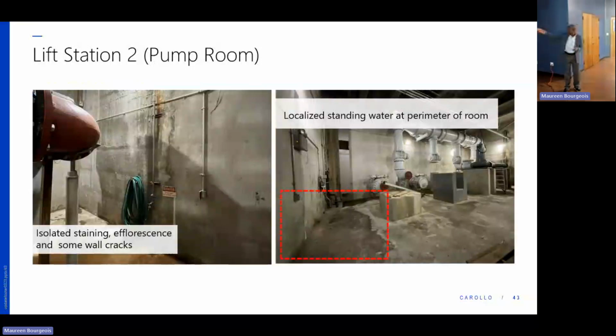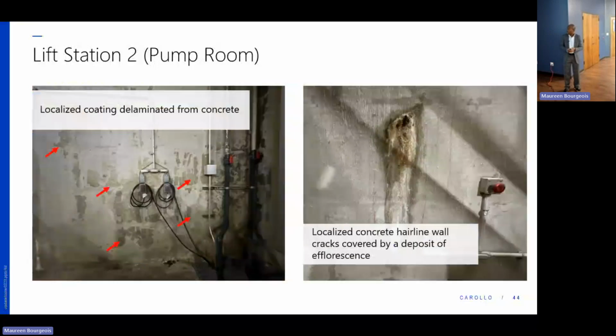At the bottom, in one localized corner, we saw water ponding at the perimeter of the wall. And that's likely coming from leaks from those cracks or some of the pipe penetrations that go through the structure. We also saw local coating coming off the wall, so delamination, falling off, peeling off from the wall. So we want to also address that. And that's the efflorescence, a zoomed in view, as you can see with the whitish substance being left behind as the water evaporates in that crack.